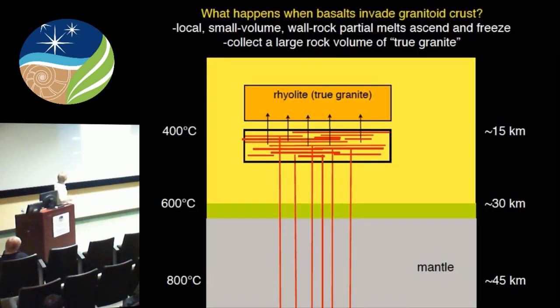So what this implies is that well before the ambient temperature in the crust is 700, there are going to be small volume partial melts that are going to form. And if they can segregate, they're going to start to come up here and freeze up slowly over time. So we're just wondering if that isn't what those zircon crystallization ages are recording. Because also there are zircon ages in the Bishop Tuff that go back to the Mesozoic. So we know zircons can get retained. And then you're going to have a volume of rock which is near eutectic. And so the question we're asking ourselves is, what would happen if a swarm of basalt, a lot of basalt in a short period of time, invaded that true granite?